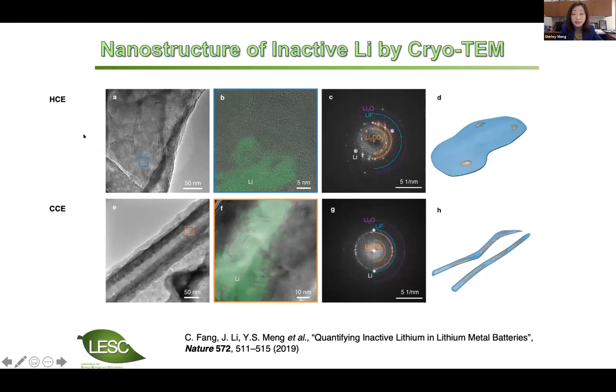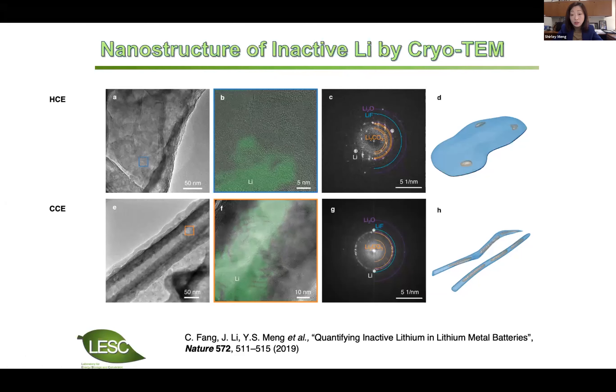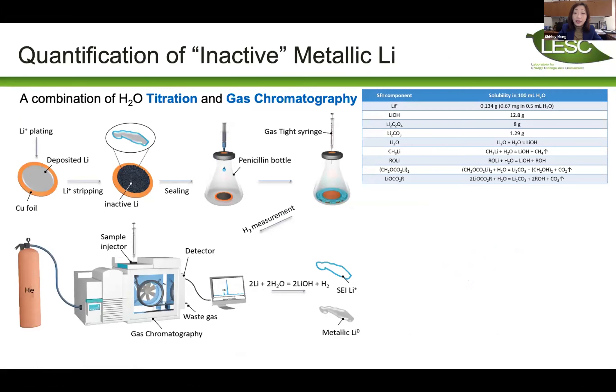The key difference we see across electrolytes: in the advanced highly concentrated electrolyte developed by PNNL, almost everything left on the current collector after stripping is SEI components — lithium oxide, lithium fluoride, lithium carbonate. In contrast, with conventional generation-two carbonate electrolyte, we see large amounts of metallic lithium remaining. However, imaging alone is qualitative, not quantitative.